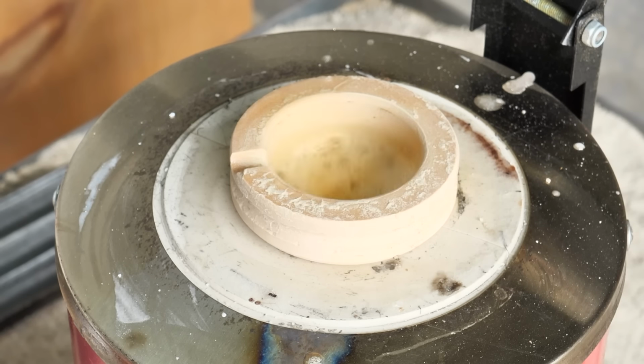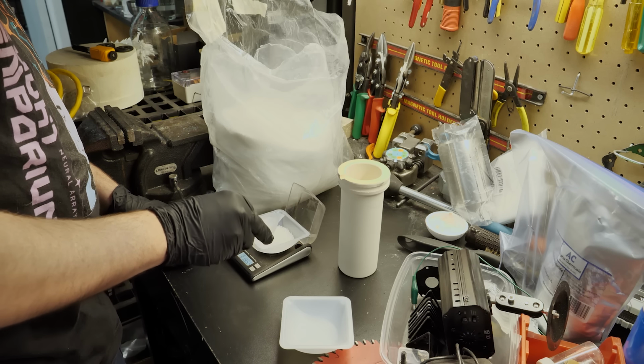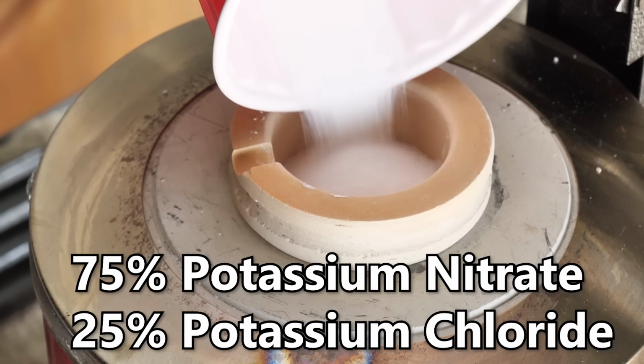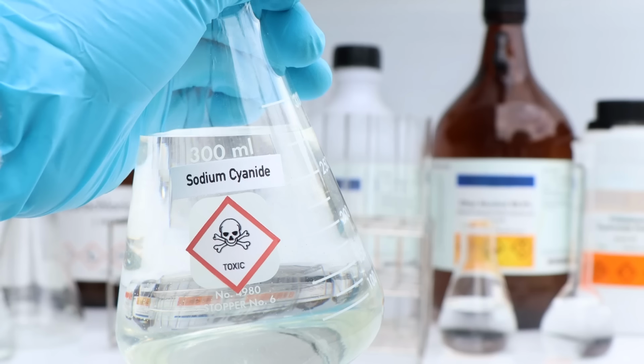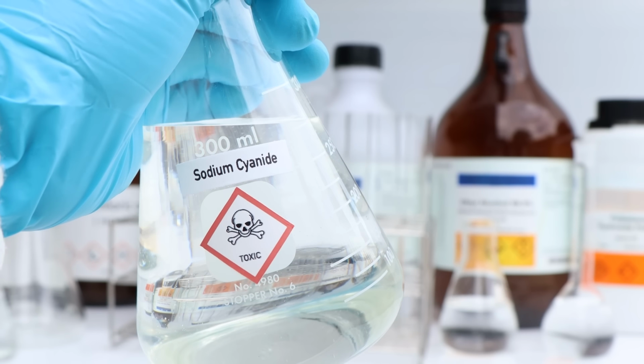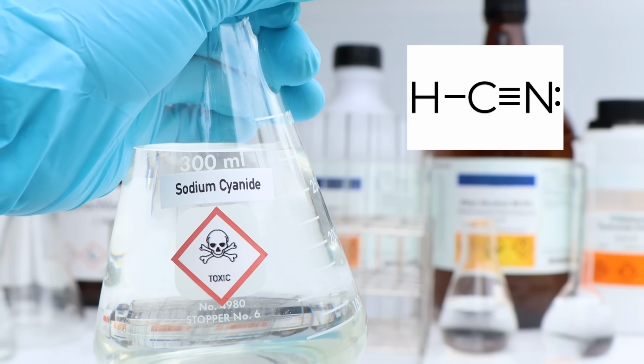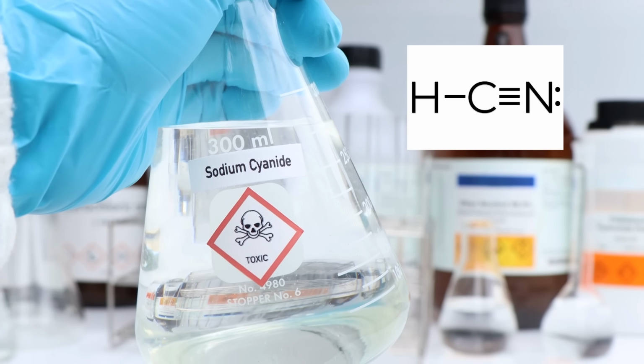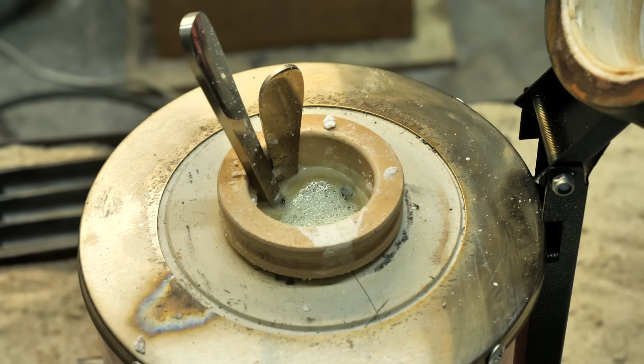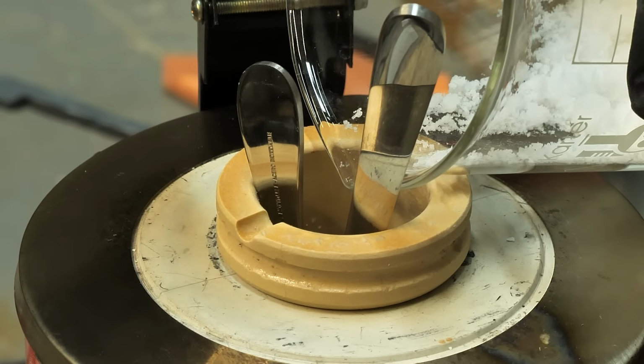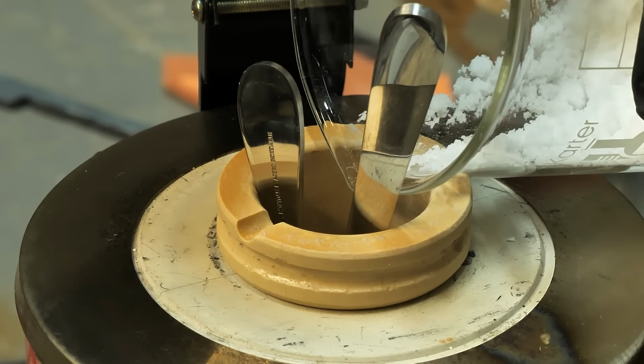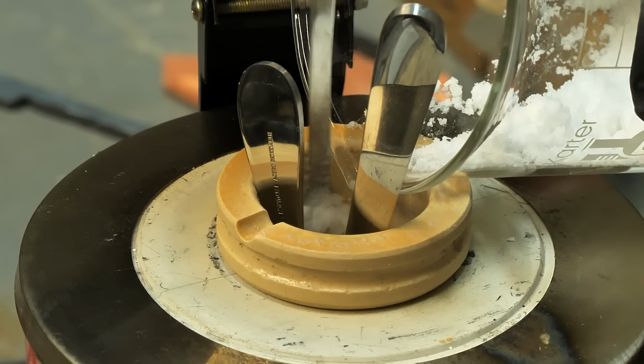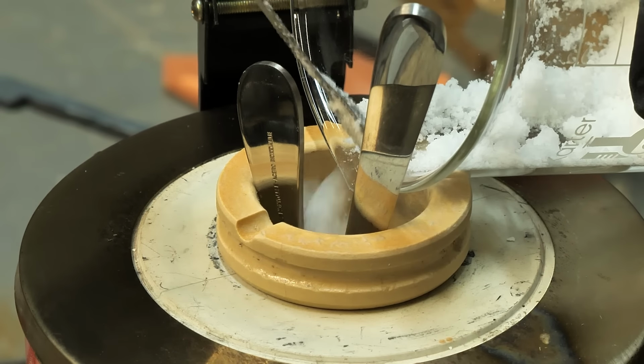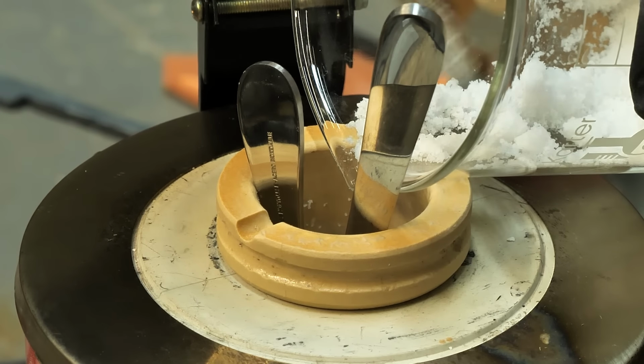Specifically molten salts. In this case, a 75 to 25% mix of potassium nitrate and potassium chloride. Industrially, they often use cyanide salts for this, as cyanide is a perfect mixture of both carbon and nitrogen, so you end up basically case hardening with both carbon and nitrogen at the same time. Of course, there's a tiny issue with this, in that molten cyanide is so unbelievably dangerous I lack the words to describe how hard I noped out of that idea. This is why we're using non-toxic potassium nitrate for this.